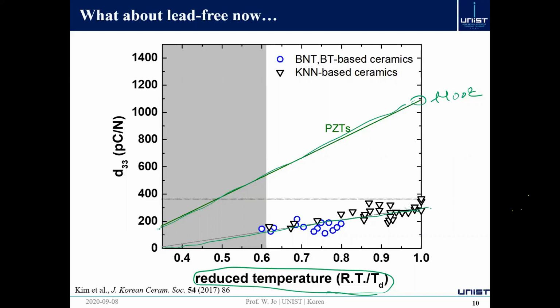And the limit of the maximum D33 we can achieve once we bring down this depolarization temperature to room temperature will be somewhere around 400. So this already explains why PZT is such an amazing material in comparison to lead-free materials. We cannot really go over this line. So again, how do you overcome this limitation?